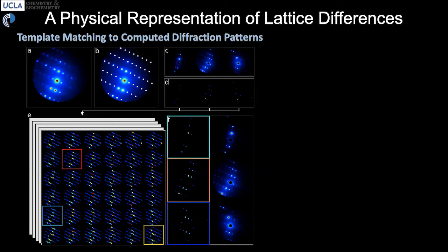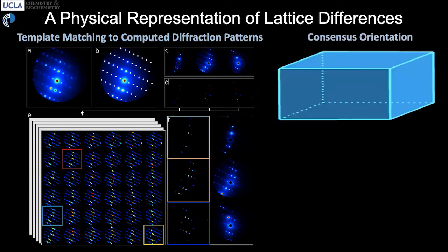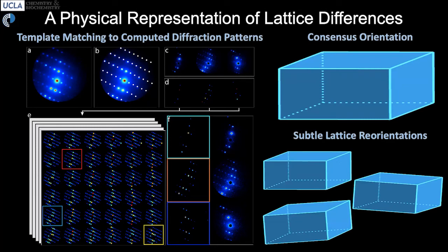Because we knew what the structure would be, in this case, this was our control sample, we could also simulate diffraction from this particular type of lattice and then compare through template matching individual diffraction patterns from particular regions of space to the simulated diffraction patterns of a lattice at a particular orientation. When we did that, we noticed that this crystal was sitting with the lattice at a particular consensus orientation. We could identify that from the ensemble average across all patterns of that crystal. But there were regions of the scan that corresponded to subtle lattice reorientations. So this was a region of the crystal where the lattice was slightly tilted with respect to the consensus orientation. Now, the tilt wasn't large, but it was noticeable, and we could detect it from the diffraction patterns.